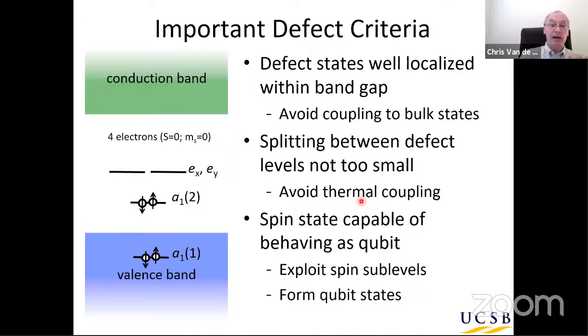So in the ground state vacancy in diamond, if you think about it, you've removed the carbon atom, you have 4 broken bonds, each of which now has an unpaired electron, so you have a total of 4 electrons. You occupy the levels I sketched here for this vacancy in diamond with these 4 electrons, and find this occupation, which corresponds to 0 spin. So for quantum application, this is not particularly interesting. Now, if you put a nitrogen atom in, you can see nitrogen has valence 5 instead of carbon valence 4. So you get an extra electron, and that electron goes into the next state here. So you actually have a spin 1/2 system, which could potentially be interesting.